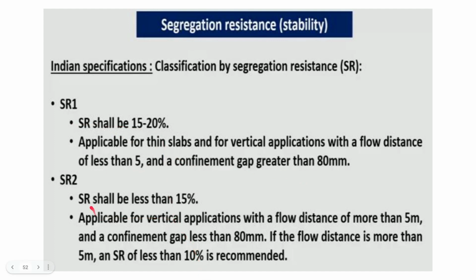But if the vertical application has a flow distance of more than 5 meter and a confinement gap is less than 80 mm, then it should be less than 15%. And if the flow distance is more than 5 meter, an SR of less than 10% is also further recommended. So basically if the flow is less than 5 meter and confinement gap is more than 80 mm, then we are allowed to have 15 to 20%. So that is the SR1 category.